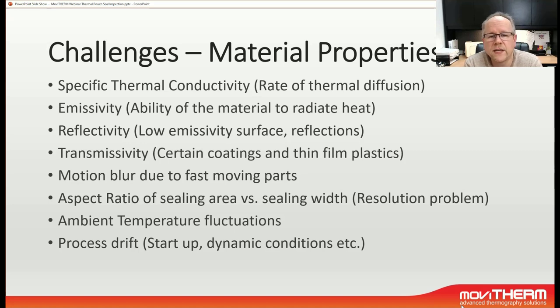The aspect ratio of sealing area versus sealing width, which we have already covered in this presentation, is to make sure that we have enough camera resolution on the sealing area. There could be ambient temperature fluctuations from winter to summer sort of thing, messing with our results. And we can also experience process drift where maybe the sealing line takes about 20 to 30 minutes or so to stabilize its temperature before we can see reliable results during the actual sealing operation. So as you can see, it's not going to be an easy task necessarily. So make sure you're working with a knowledgeable company that understands what they're doing.